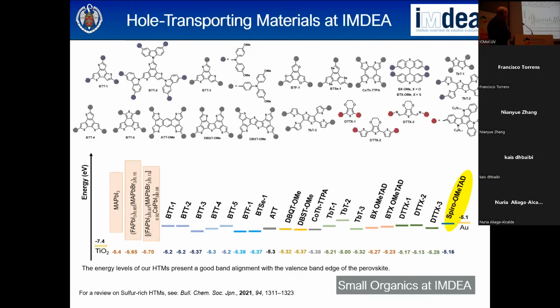So these are most of the molecules we synthesized, but look at the energy alignment, it is pretty good. This is the spiro as the reference, and you see that the HOMO level fits in all our molecules. This is gold. And these are the different perovskites, the monocation, the MAPI, the dications, and the state of the art with the trication perovskites. But the HOMO-LUMO levels of the perovskites are in agreement to be used with all these materials. So this is interesting to know.